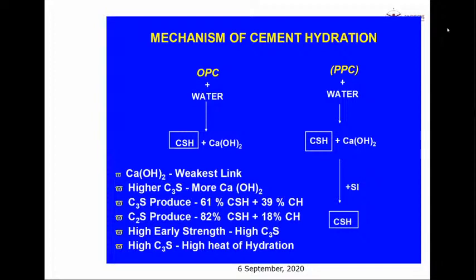Now, what happens when OPC is combining with water? It forms something called the calcium silicate hydrate gel, CSH gel, and it also forms lime, calcium hydroxide. This calcium hydroxide is very much essential for the concrete because it ensures that the concrete stays alkaline. It also plays a vital role in blocking the finer pores of the concrete matrix.